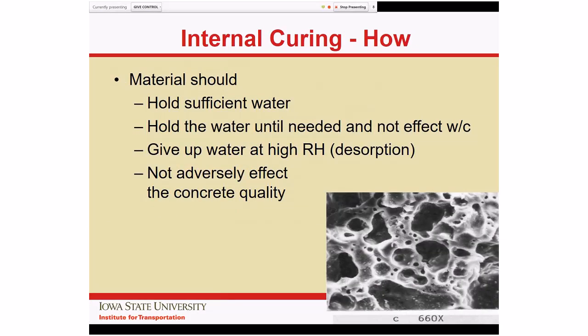So how do we do this? I talked magically about trapping little bubbles of water inside the concrete. Now the one catch with this is that we don't want to just add water to the mix, because then you're changing the water cement ratio at the time of mixing, and that's a big fat negative. The way we do it in the US is to use lightweight fine aggregates. So fundamentally, the material should hold enough water. That's pretty obvious. It should hold the water until it's needed without affecting the water cement ratio. It should give up the water when we want it and not have any other negative effects on the quality of the concrete. And a dosage of lightweight fine aggregate seems to hit all of these buttons.